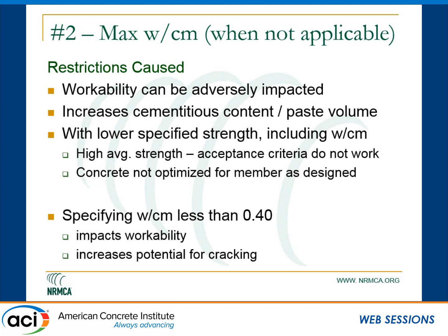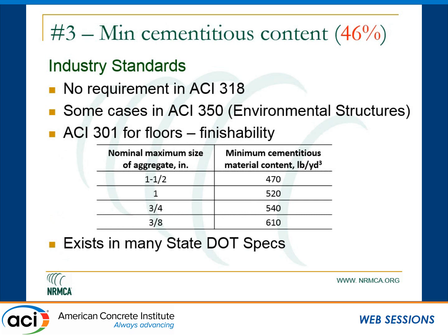When we have a low water cement ratio, we really have a problem sometimes with workability when it gets too low, when it's unnecessary for certain applications. You also tend to increase the paste volume of the mix, which causes other problems with the concrete mixtures. And it's really not necessary for most of our applications to specify a water cement ratio less than 0.4, unless you're getting into very severe type exposures.